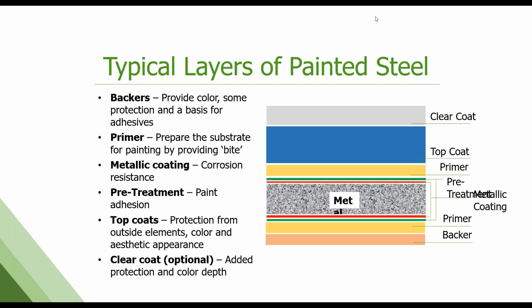So when we're done, we've got quite a few layers going on in the final product. You have your base metal in the middle there, which is the majority of the thickness of the final product. If it's a coated steel product, it's then going to have a metallic coating of either galvanized or Galvalume, which is the zinc aluminum coating on it. Then the very thin layer of pre-treatment to help promote adhesion for the paint system. And then your primer. Your primer does a couple of things. It provides a lot of corrosion protection, but it also preps the surface for that top coat, so you get nice even coverage and color. And again, good adhesion, good flexibility can come from your primer as well.